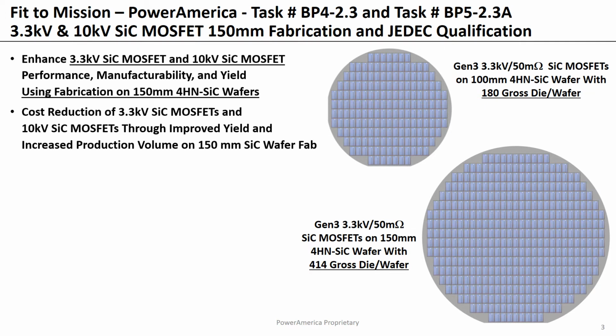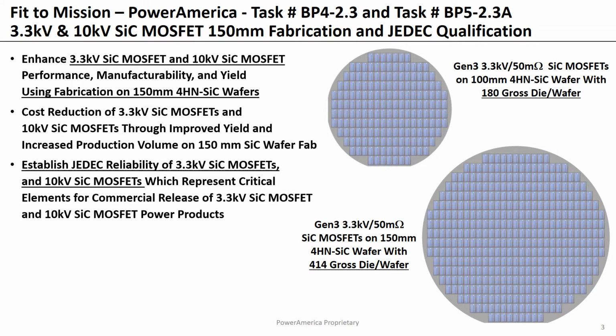A similar analysis shows that for the 10 kV 220 milliohm silicon carbide MOSFETs, there's more than a 2x increase in the number of these 10 kilovolt silicon carbide MOSFET die printed on the 150 millimeter wafer compared to the 100 millimeter wafer. We also need to establish JEDEC reliability of 3.3 and 10 kilovolt silicon carbide MOSFETs because they represent critical elements for the ultimate commercial release of 3.3 kilovolt silicon carbide MOSFET and 10 kilovolt silicon carbide MOSFET power products, including both device die and modules.